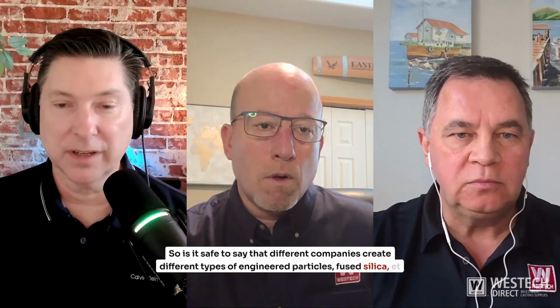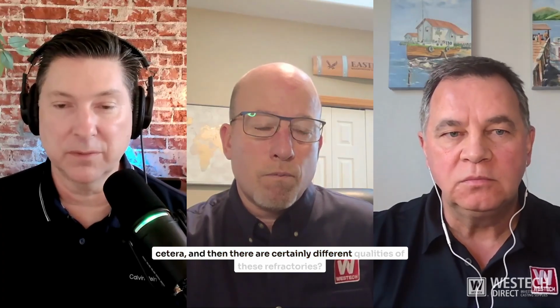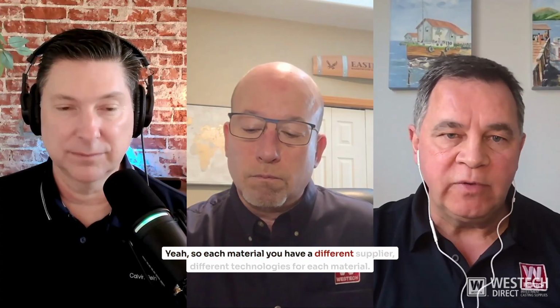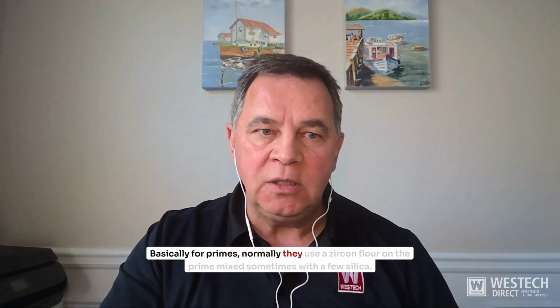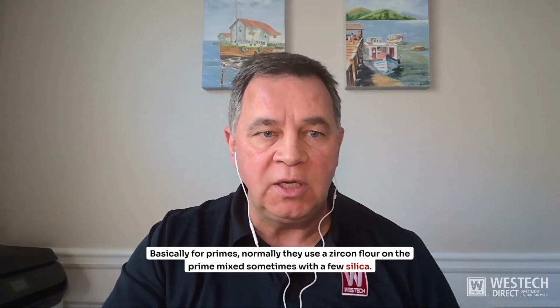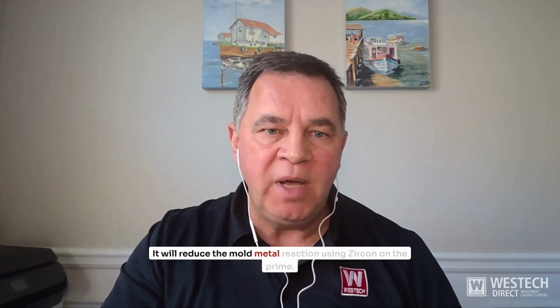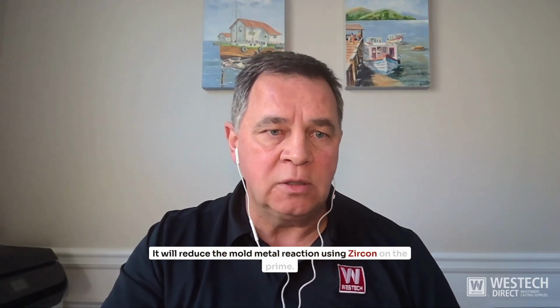So is it safe to say that different companies create different types of engineered particles, fused silica, et cetera, and then there are certainly different qualities of these refractories? Eduardo? Yeah, so each material, you have a different supplier, different technologies for each material. Basically, for primes, normally they use a zircon flour on the prime, mixed sometimes with the fused silica. It will reduce the mold metal reaction using zircon on the prime.